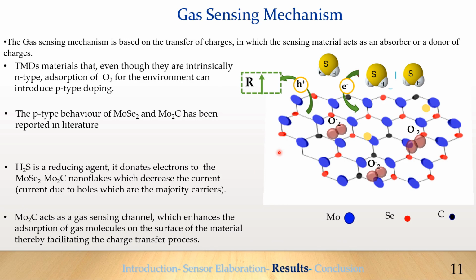The basic principle of gas sensing in hybrid material is mainly based on the charge transfer processes between gas molecules and the surface of sensing materials. TMDs behave as N-type semiconductors intrinsically. The adsorption of oxygen molecules from the environment can introduce p-type doping of MoSe2-Mo2C devices by increasing the hole density. When exposed to H2S, a reducing gas, the material acts as a charge acceptor, which leads to an increase of negative charge, and the number of holes decreases, which leads to the resistance increase.